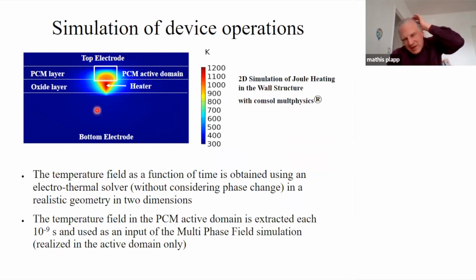Now, here comes the simulation of memory operation. So for this, we combined our phase field model with a macroscopic electrothermal solver. So this is a program that solves the combined electrical and thermal problem and calculates the time-dependent thermal field in a memory contact as a function of time. So the white frame here, this is the active cell. So this is our simulation cell for the phase field model. Here below is this heater electrode, which will emit heat when it is traversed by a current. And so here the colorful shades are the temperature field. And so we sample this and we feed this as an input in our phase field model.